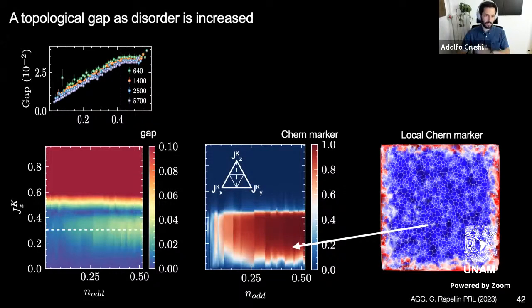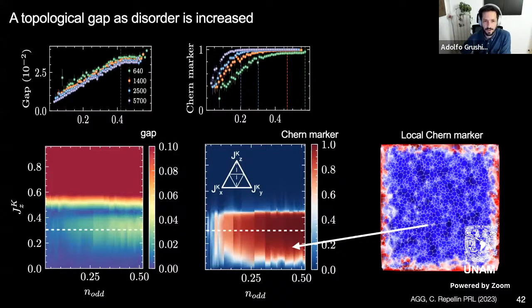And so the system that I was showing you before is over here where the gap is saturated, but in fact, you don't need to be fully amorphous to have a sizable gap. In fact, what it looks like is that any disorder, any number of odd sites, of odd plaquettes, sorry, will give you a steadily increasing gap. And the same you can do with the Chern marker.